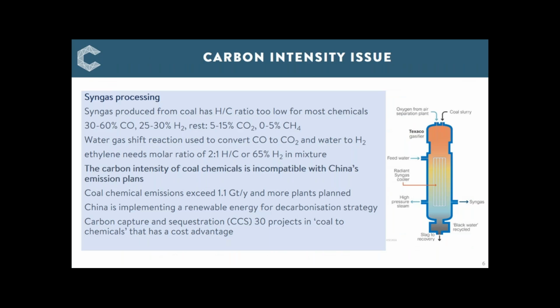This is to talk about carbon intensity, and we've been talking about 3 or 4 tons of coal per ton of product. On the right is the Texaco gasifier. The initial expansion of the industry was based on gasification reactors such as this one, using oxygen and a coal slurry. There are other variants in the technology, and China is developing their own reactors that are more suited for lower quality coal, and also to take in bio feedstocks and waste feedstocks as well.